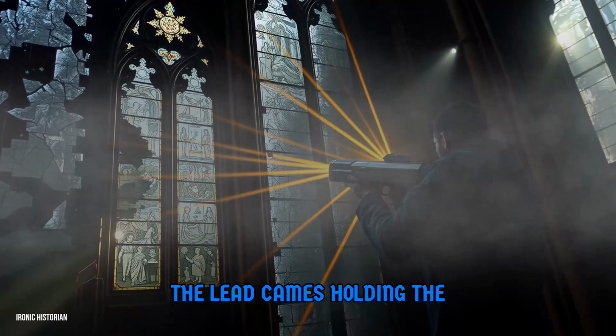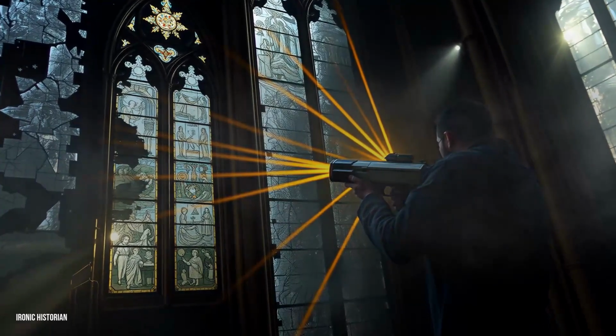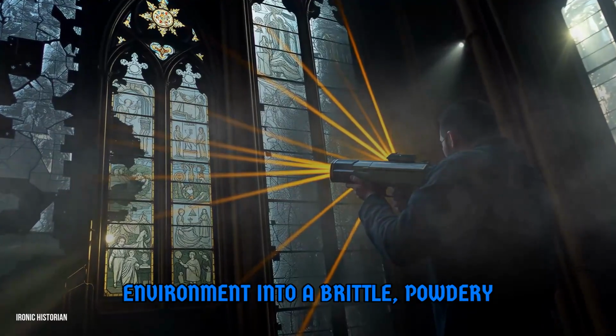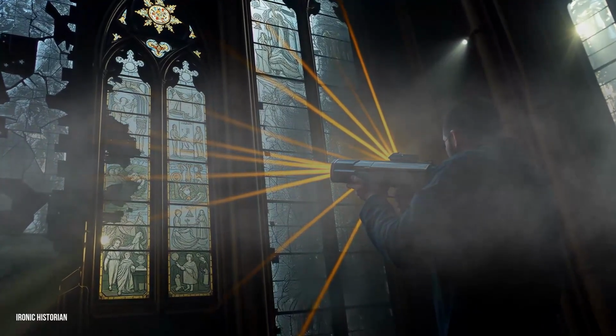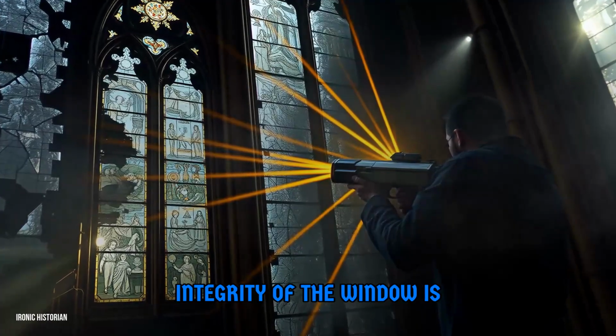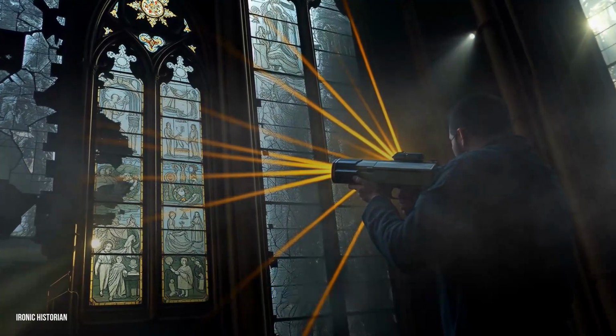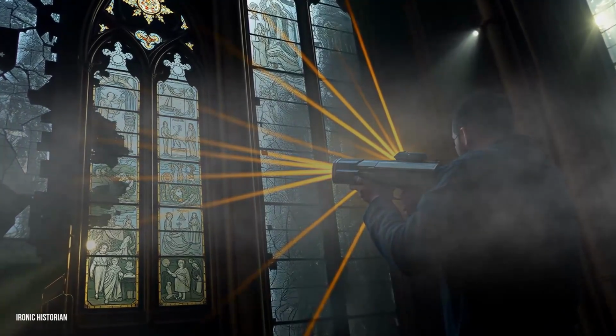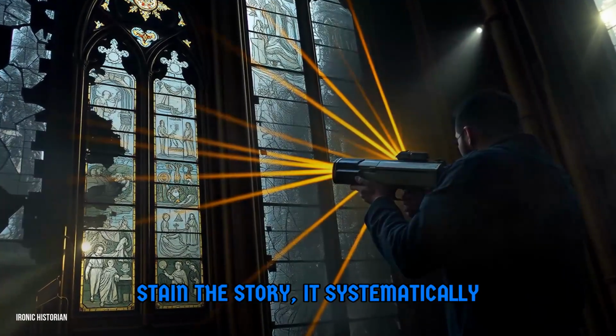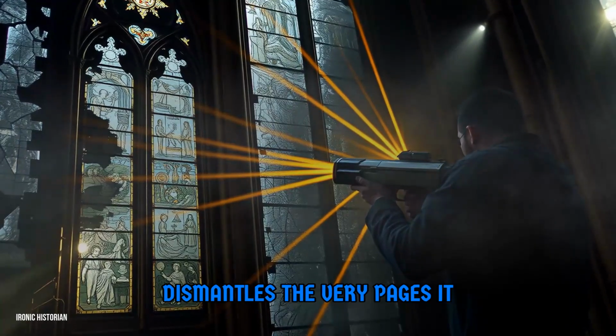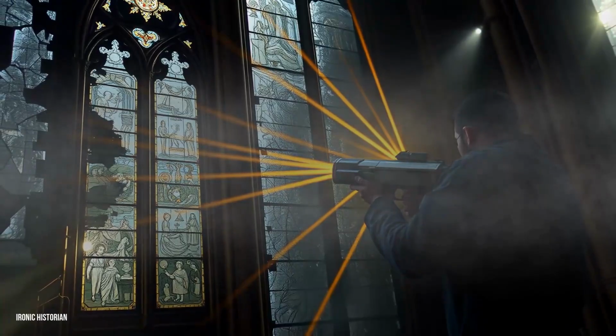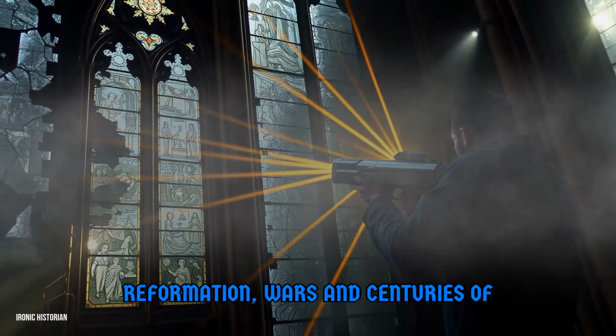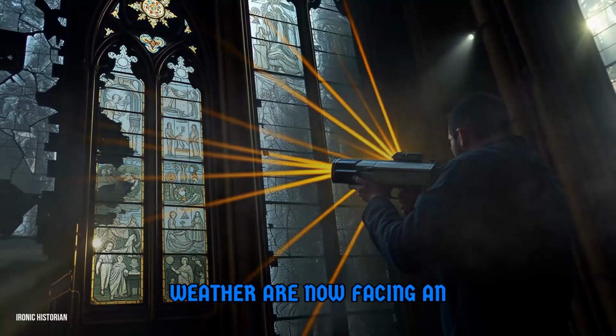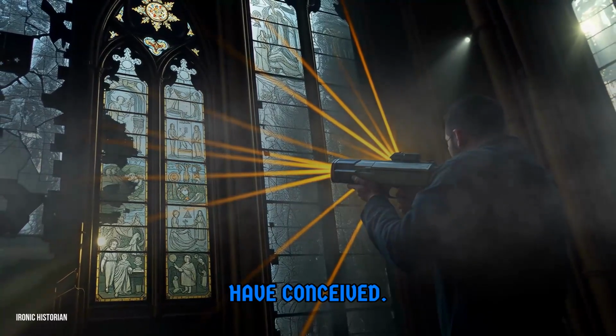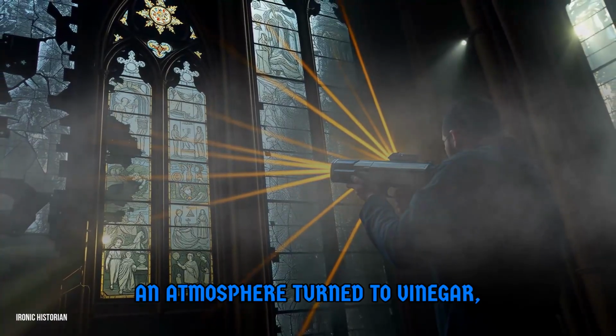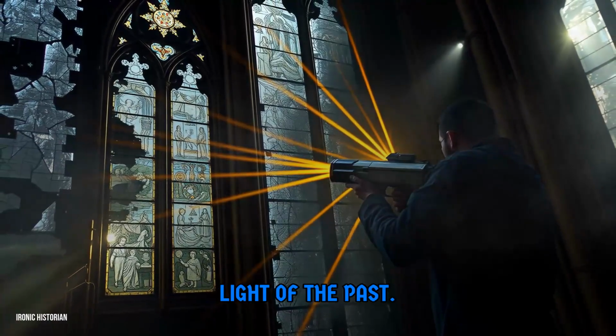The lead cames holding the panel together are also attacked, corroded by the same acidic environment into a brittle, powdery state. This means the entire structural integrity of the window is under assault, from both the glass and its metal skeleton. Acid rain does not just stain the story, it systematically dismantles the very pages it is written on. The windows that survived the Reformation, wars, and centuries of weather are now facing an enemy their makers could never have conceived. An atmosphere turned to vinegar, silently eating away at the light of the past.